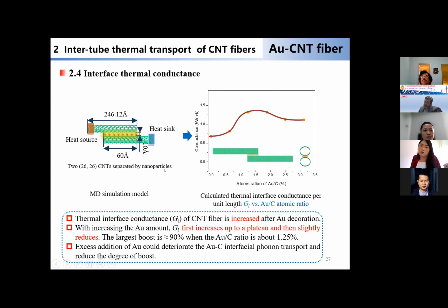This boosted phonon transport was further investigated by molecular dynamics simulations. Interestingly, with increased gold nanoparticle amount, the interface conductance first increases up to a plateau and then slightly reduces. We would deduce that the excess addition of gold could possibly deteriorate the gold-carbon interfacial phonon transport and reduce the degree of boost.